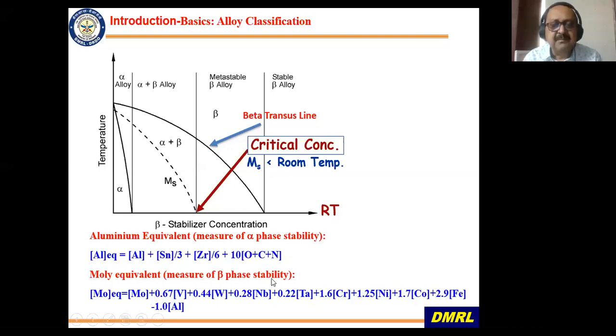Then, as a measure of beta stabilization, you have what is known as moly equivalent, and you have all the elements with a multiplication factor. And aluminium does decrease the moly equivalent or beta stabilization, so it is negative. And if you look at this formula, the iron is one of the strongest beta stabilizing elements, so it has got a multiplying factor of 2.9, and then there's nickel, cobalt, chromium, etc. are there, and moly is 1.